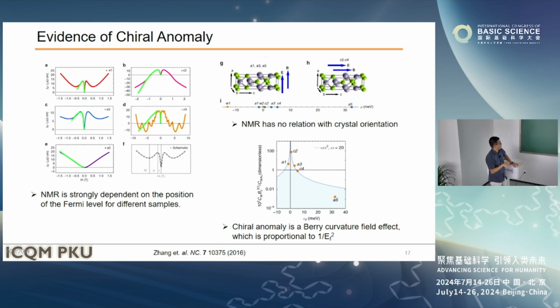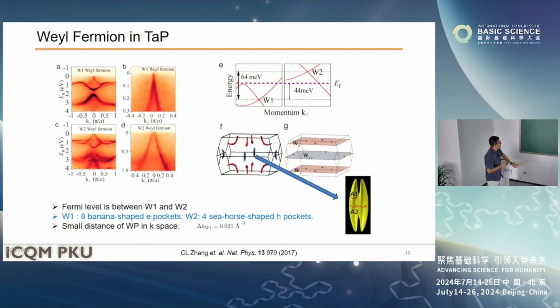And we use the quantum oscillation of this compound to determine the position of the Fermi level. And we collaborated with some theorists on the chiral anomaly. It can be well understood as a Berry curvature effect, meaning the negative magnetoresistance is proportional to 1 over E_F squared. Meaning when the Fermi energy is closer to the Weyl point, we have a stronger chiral anomaly. When it's away from that, we almost cannot see it, like in this one. So this is strong evidence that we really observe a chiral anomaly instead of a current jetting effect.